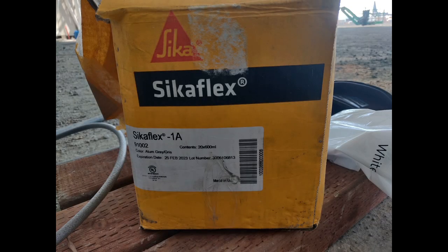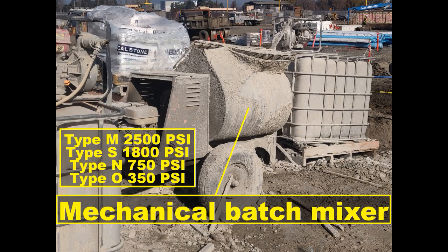Admixtures for masonry mortar. In cold weather, use a non-chloride-based accelerating admixture that conforms to ASTM C1384, unless Type 3 Portland cement is used. In showers and kitchens, use mortar that contains a water-repellent admixture conforming to ASTM C1384. Provide a water-repellent admixture conforming to ASTM C1384, of the same brand and manufacturer as the block's integral water repellent, in the mortar used to place concrete masonry units that have an integral water-repellent admixture.